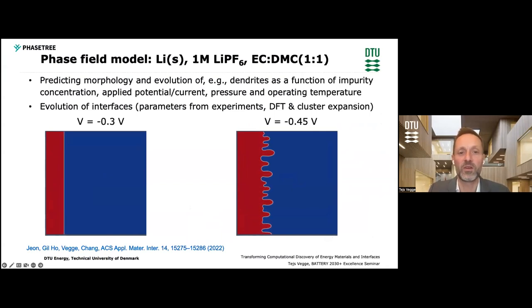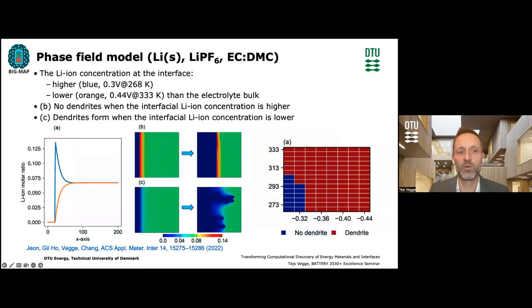And you can see for this specific combination of temperature and pressure, if you're too aggressive, you actually start forming dendrites in the battery. So you can identify the conditions, or you can see what would be needed in order to modify the composition or the temperature to suppress dendritic growth. So you would have a tool available that would tell you under these conditions, these are the overpotential, these are the conditions in terms of temperature. You can deduce parts of the underlying physics: you don't form the dendrites if the interfacial concentration of the lithium ions is high, but you form them when it's low, and you can see what is the safe operational window.